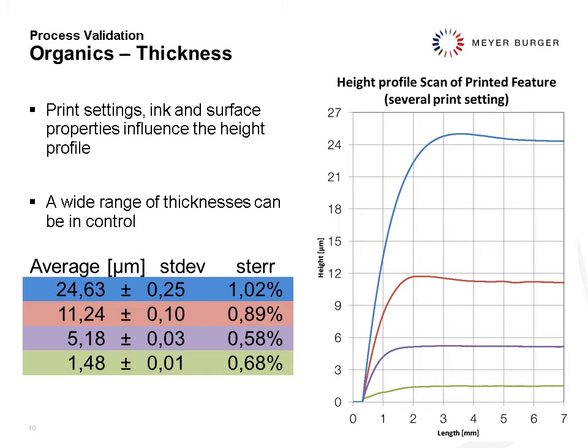What we have been testing in our laboratories is that with the same ink and same surface, we were able to do a wide range of thickness. Of course, we had to change print settings, and the good thing was the uniformity of this layer. From a certain moment on, we can ensure that the layer will be flat with a standard deviation which is approximately 1% of the average value.